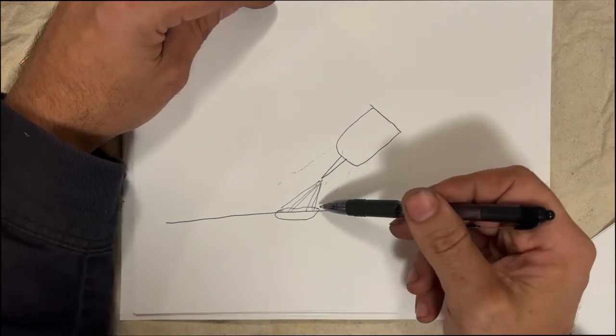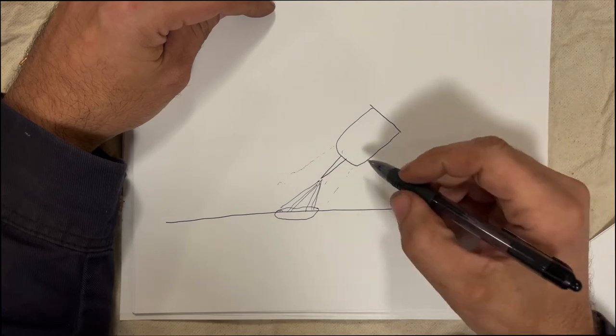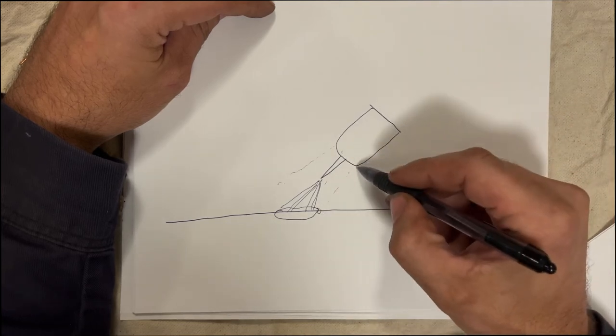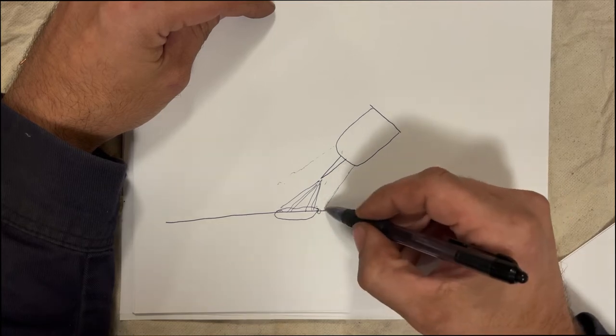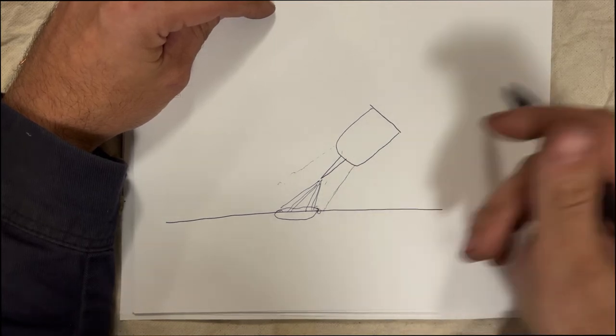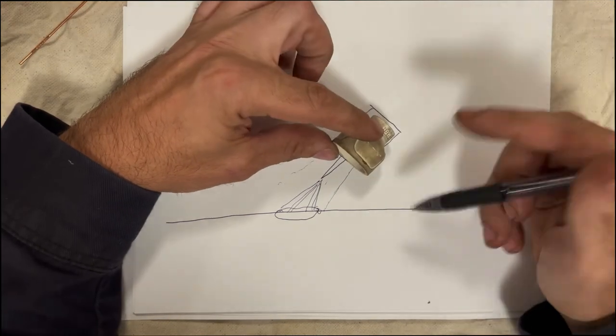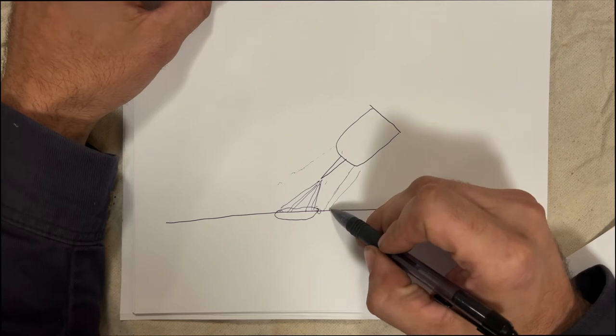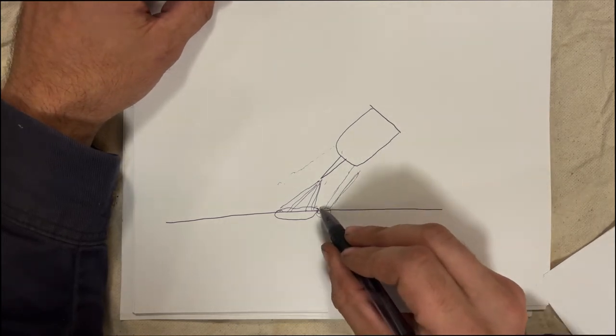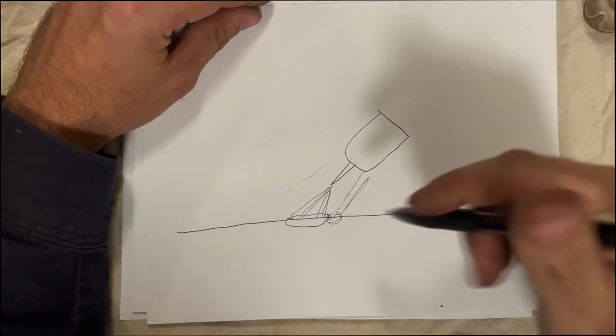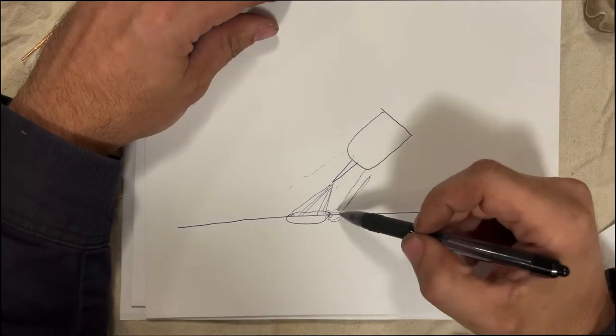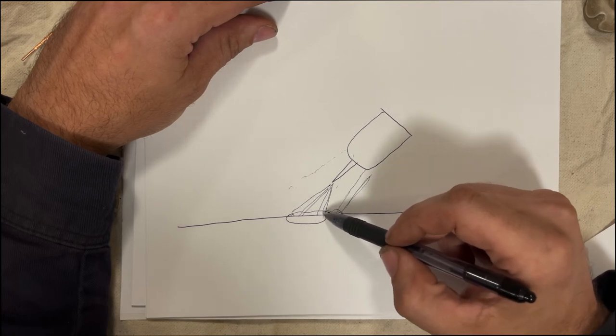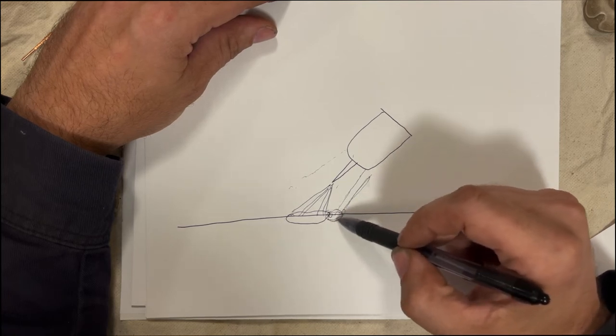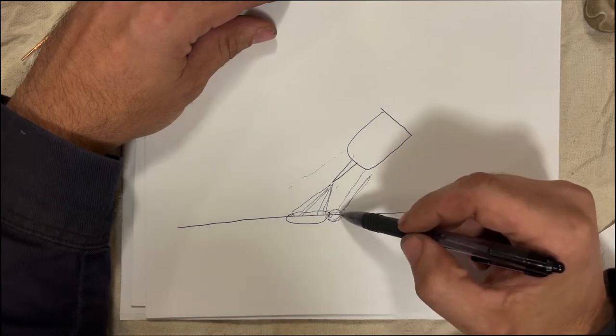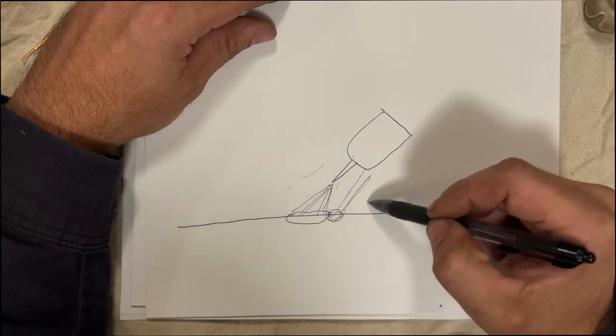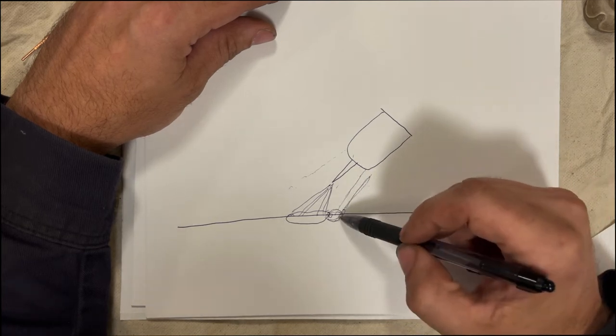As you progress forward with your weld, the area that's shielded behind the cup, as you can see, the gas is coming out here, isn't really a very long distance. So by going with a wider cup, like here, your gas shielding actually exists further back here, which is, this area is bigger. That's important and relevant because, especially with stainless steel, as that weld turns from molten to solidified in this zone here, the hotter it is when it's exposed to oxygen, which is back here out of the shielding gas area, it will form oxide.